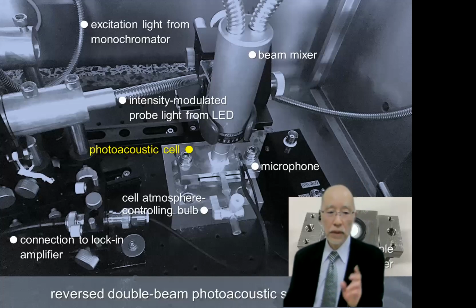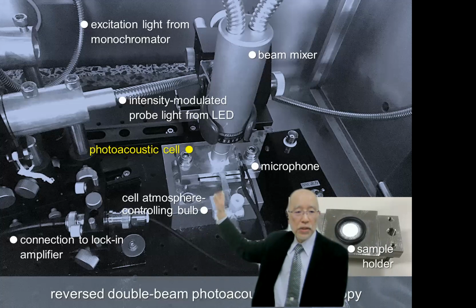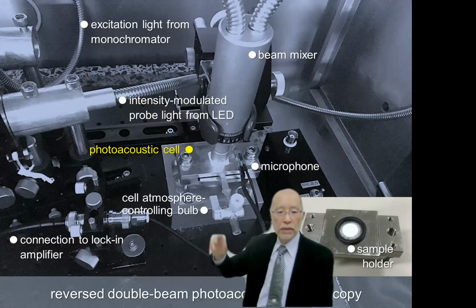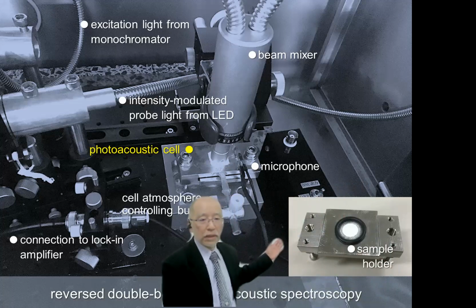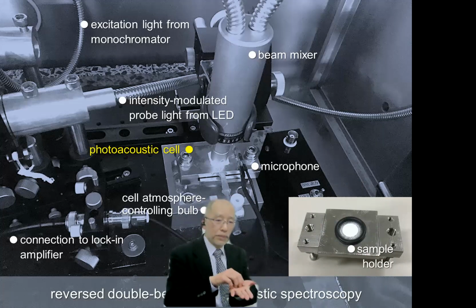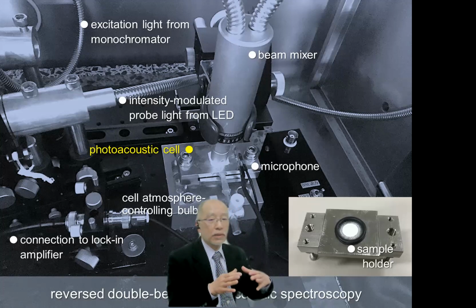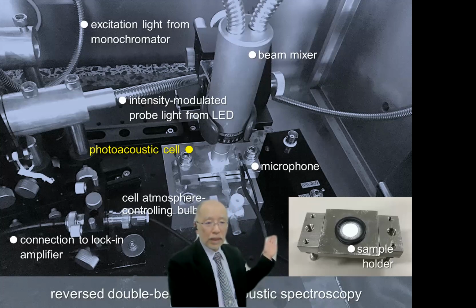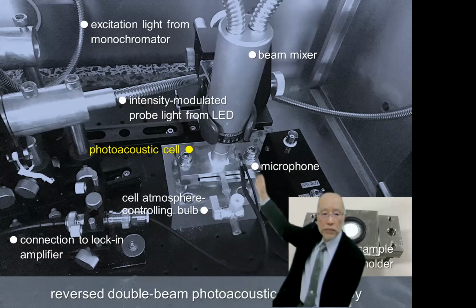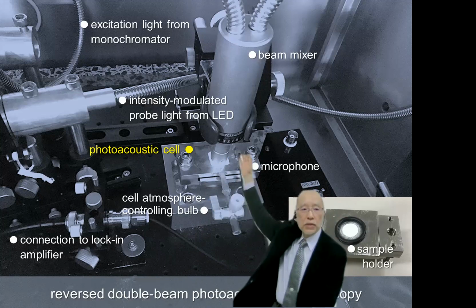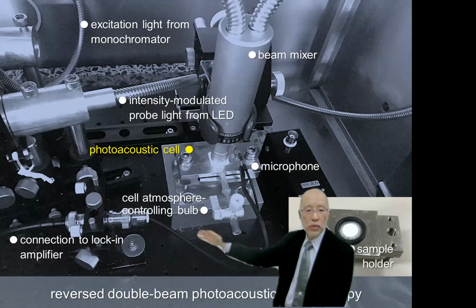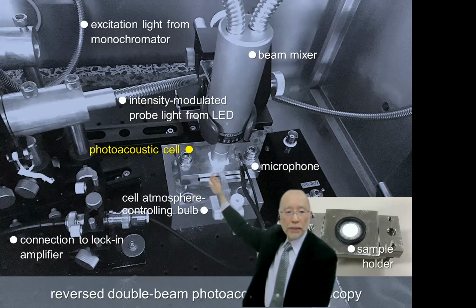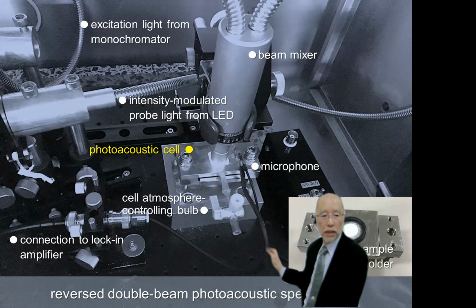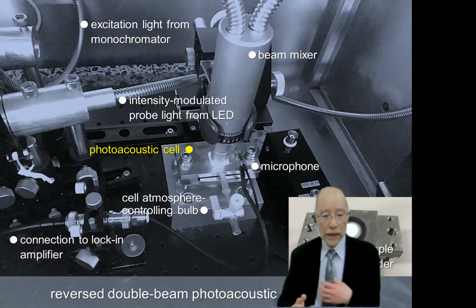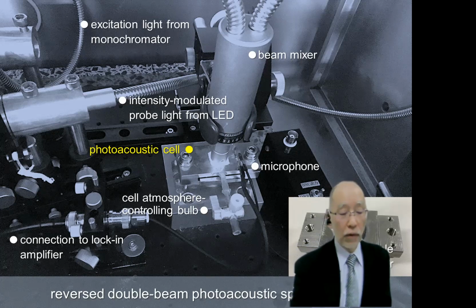And this is a real setup. This is just an old one, but the principle is the same. This is a cell, and inside the cell the sample is loaded like this. That is almost the same as for XRD: in the dimple, the powder sample is filled. Also a thin film material on a substrate can be measured using the same technique. In the cell, the microphone is equipped, and the two beams are combined by the beam mixer and introduced to the sample cell. The detection of the signal from the microphone can be made by using the lock-in amplifier.